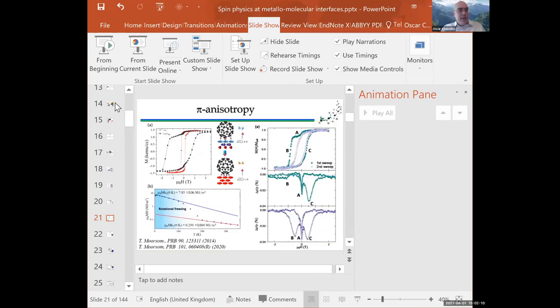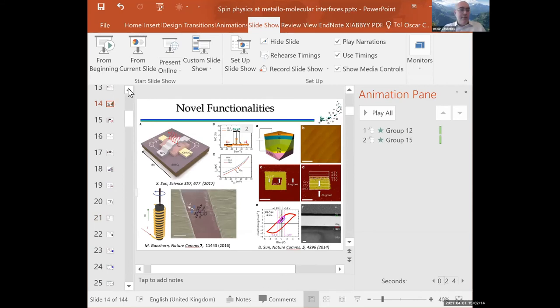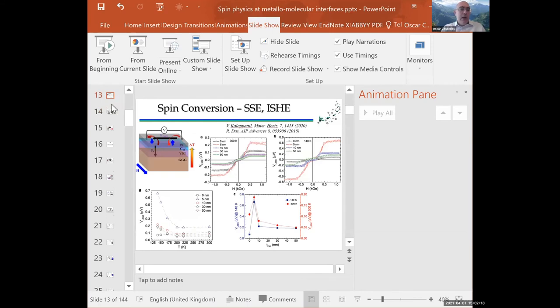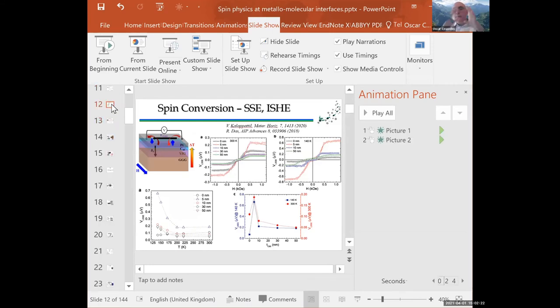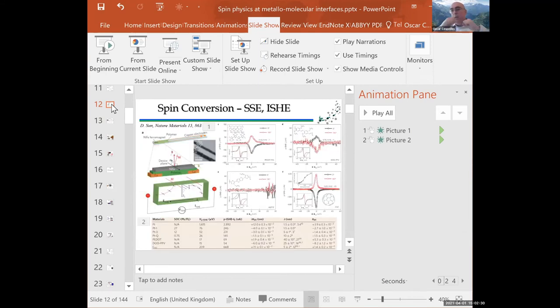So this was already reported by Vardeny in Utah, that they have a very large inverse spin Hall effect in C60. And the only reason I can think of for that is the curvature of the molecule. So in carbon molecules, you are going to have a larger spin orbit coupling because you have your orbitals deformed. In graphene, you would expect no contribution, obviously, because it's perfectly flat. But in C60, which is one of the smallest of the fullerene molecules, this can be very large. And this was also observed a long time ago in people who were doing measurements in carbon nanotubes. So when you have a single wall carbon nanotube with a very small diameter and very high curvature, then you can see a very large spin orbit coupling on those molecules. So in my opinion, that's where the intrinsic large spin orbit coupling of C60 might be coming from.